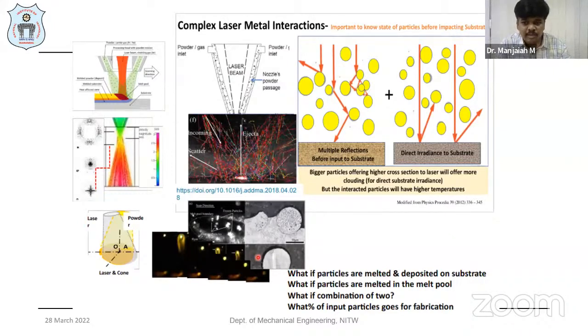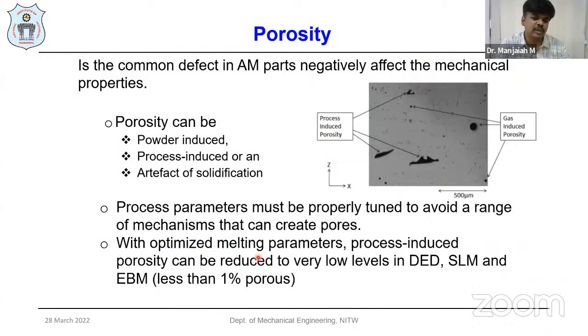If the particles are melted and maybe deposited on the substrate, what if the particles are melted in the melt pool itself? And maybe a combination of both, and what percentage of input particles goes into the fabrication? I mean, we assume that in DED systems we are supplying 100% of the powder feeding, but melting and solidification takes place for only about 60%. We may not melt 100% of the powders supplied from the feeding nozzles, because of the loss of powder particles from spattering or ejecting from the melt pool. Only 40 to 60% melting efficiency is there in the DED system.